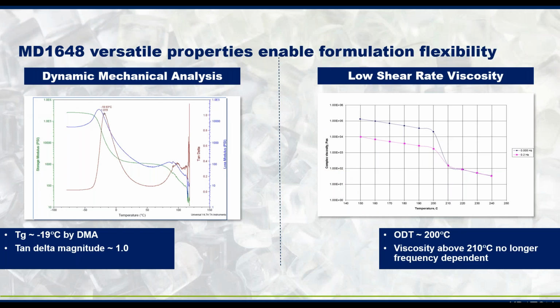Here are some experimental analysis of the MD1648 that provide understanding of the polymer itself and how to process it for success. On the left side, the DMA results show a two-phase structure with a relatively low Tg of negative 19 degrees Celsius. And on the right side, you can see that MD1648 has a lower order-disorder transition temperature compared to other more conventional grades, allowing this material to be processed at a lower temperature and therefore can become a single phase much faster.